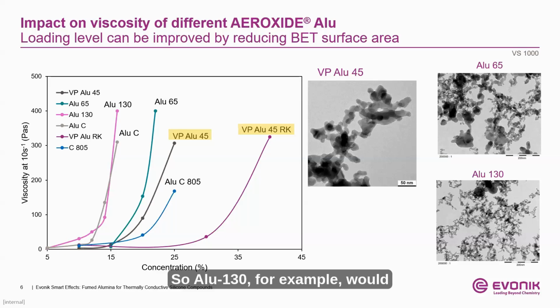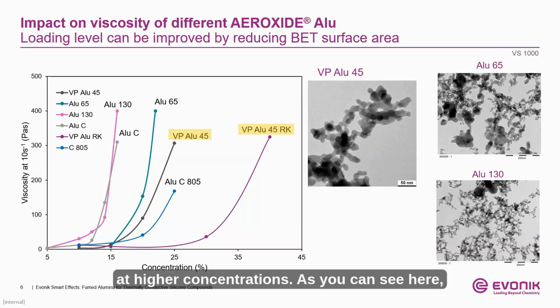So Alu 130, for example, would have a specific surface area of 130 meters squared per gram. Alu 65 would be 65 meters squared per gram, so on and so forth. The AluC and the AluC 805, C being the Roman numeral for 100, would be a specific surface area of 100 meters squared per gram, just to explain that nomenclature there. The two VP products we have highlighted, the 45 and the 45RK, were developed to reduce viscosity at higher concentrations.